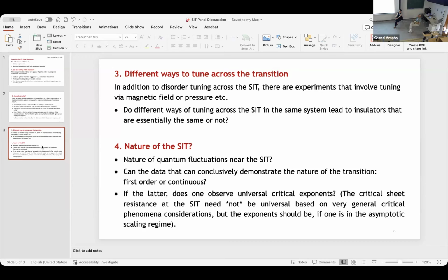So now comes the question of this Cooper pair glass order parameter, and they could have some estimates for the energy scale, whatever you call it. And in it, you have Coulomb, so you put in a dielectric constant. If you put in a dielectric constant, then you come back to condensed matter, and the materials may have a different one. So some can have a large Coulombic effect, others less, and you may or may not see a stronger or smaller jump at the transition. This is how I interpret these differences, in light of this theory, that it's just a theory.